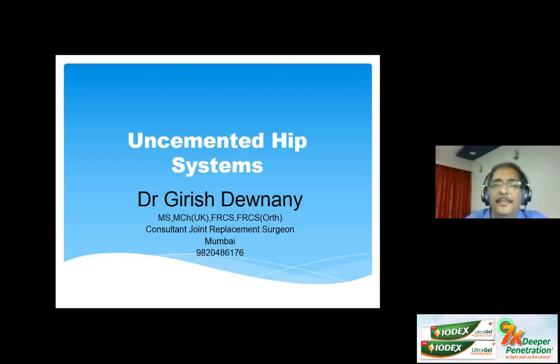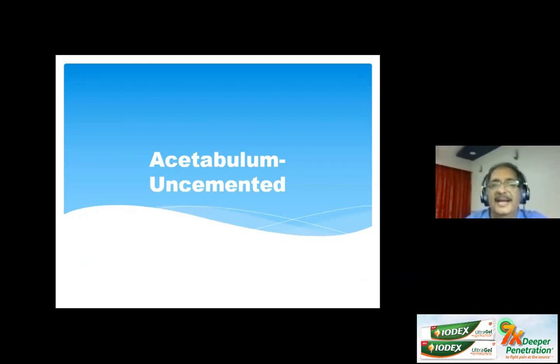These are certainly gaining in popularity. And first, we move on to the acetabulum. Now, an interesting situation which I would like to share is in 2000, when I attended the American Academy of Orthopaedic Surgeons meeting in the US, about 98% of all arthroplasty surgeons were using an uncemented acetabulum. And at that stage, I was in training and working in the UK, where about 50% of surgeons were using uncemented and 50% were using cemented. And the usual refrain in the UK was that the Americans don't know how to cement, and that is why they're using an uncemented system, which I think was very clearly brought out by Atul's talk, which specified how important the technique is to get a good result.